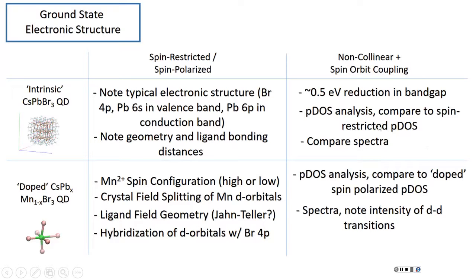So it'd be interesting just to compare the orbital analysis for HOMO and LUMO for both systems. And also compare spectra, because there could be changes in oscillator strengths too if there are changes in the orbitals for all the states. And then for the doped system with non-collinear and spin orbit coupling, same thing, PDOS analysis, seeing how the orbitals change with the inclusion of spin orbit, and noting the spectra, and then we're able to see d-d transitions, or spin flip transitions from the metal dopant, and then note the intensity of them, because it's there, but it's very, very small, very weak.